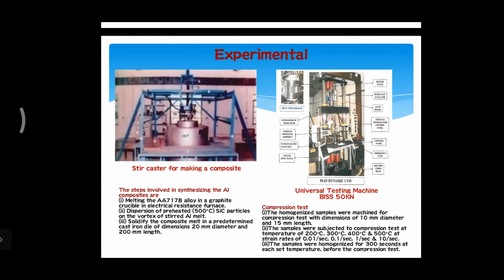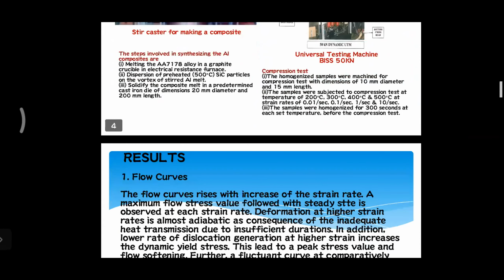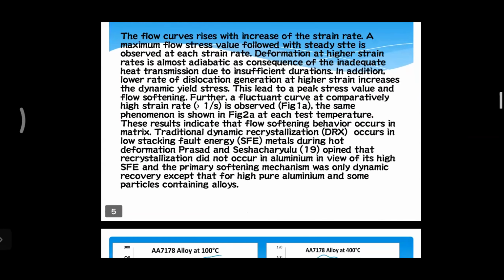We made samples of 10 mm diameter and 15 mm length, and compressed them at 200, 300, 400, and 500 degrees Celsius, and at different strain rates from 0.01 per second to 10 per second. Using 4 or 5 different strain rates and temperatures, we draw the plots, so we have to draw the flow curves.